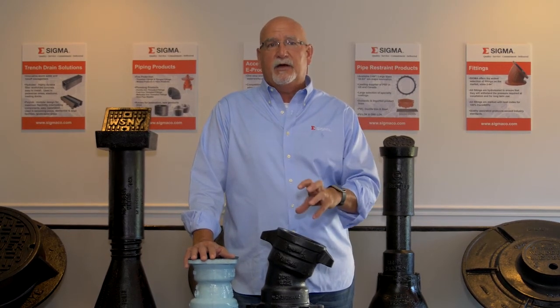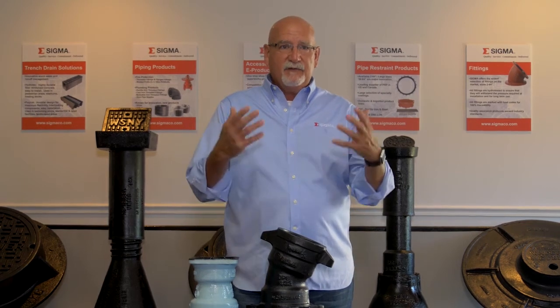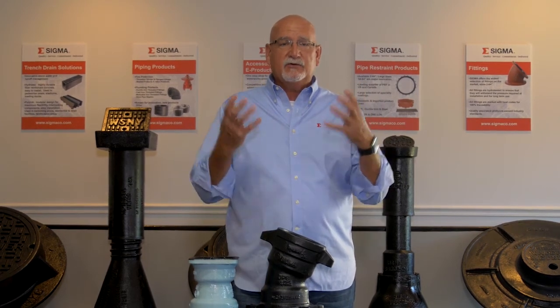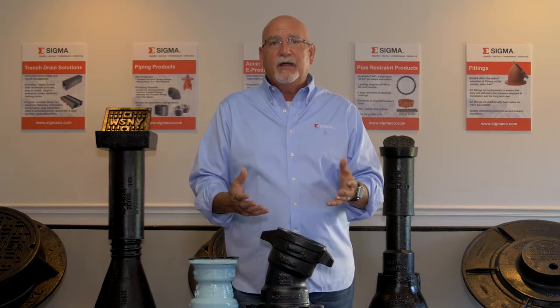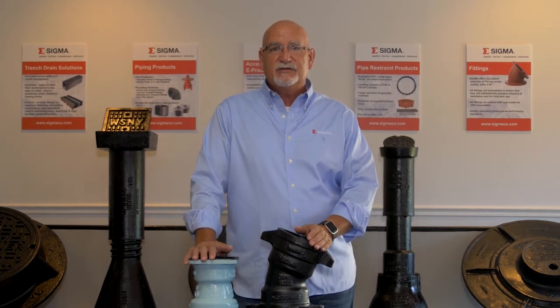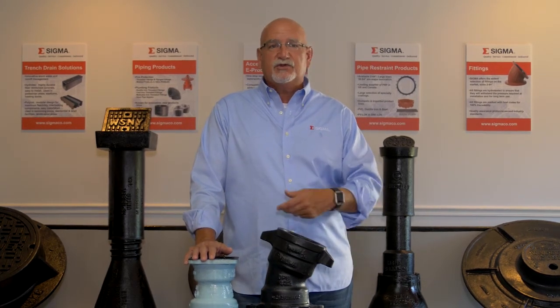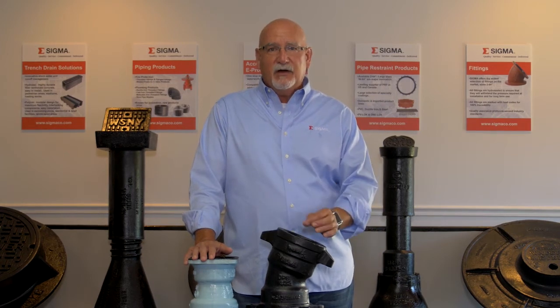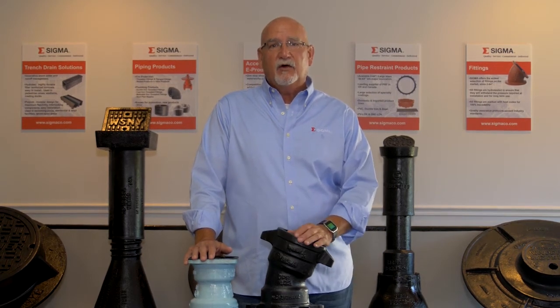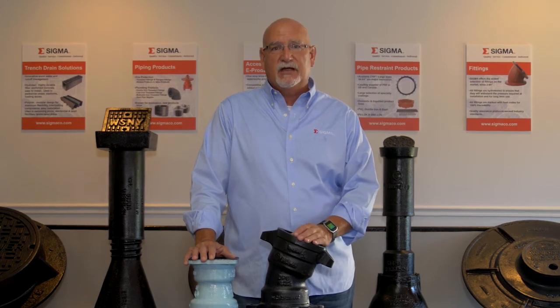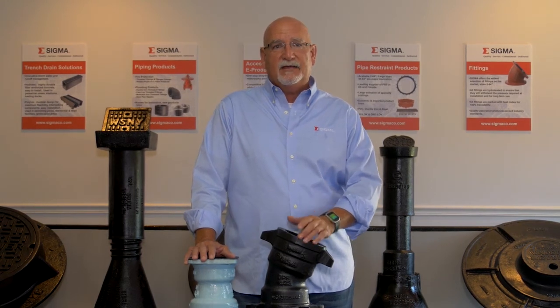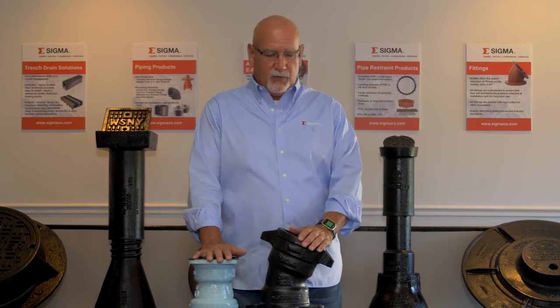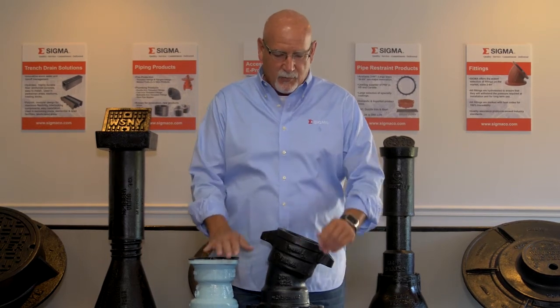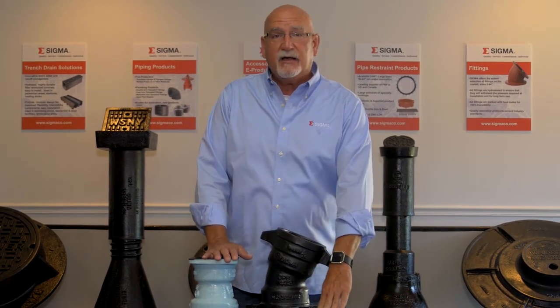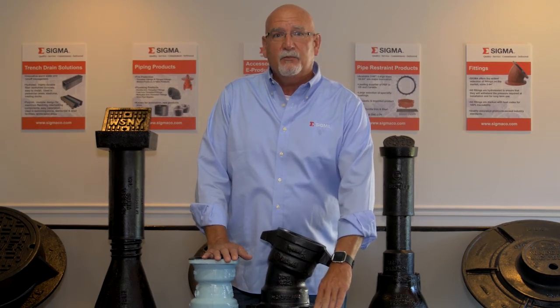In an E-coated product, since it's in a bath of liquid and has an electrical charge applied to it, the only way to get any damage to the surface is for it to be struck or scratched, and that is very difficult with the type of E-coating material we use. It's very tough and scratch resistant. So that's kind of a primer on what we do to coat our restraints. The standard is epoxy, but the material is also available with E-coat and an epoxy top coat.